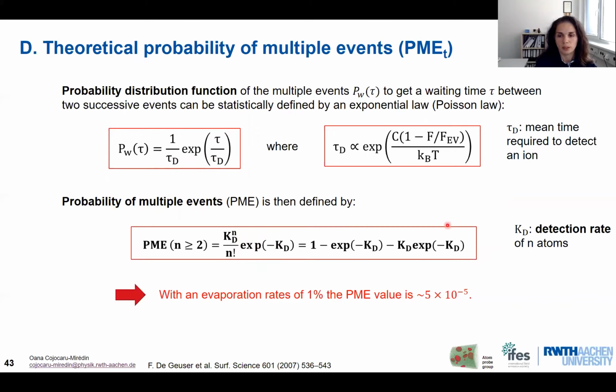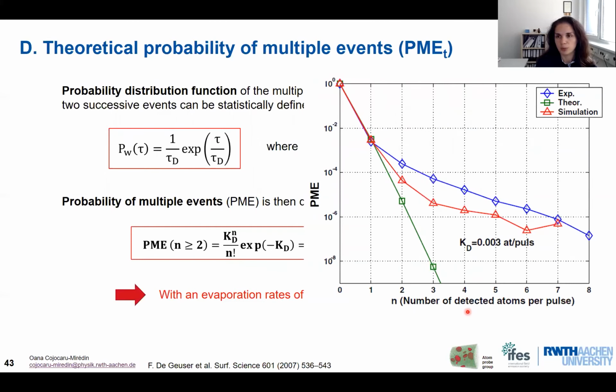If we then take, for example, the detection rate of about 1%, which we usually use for atom probe experiments, we see that we end up having a theoretical probability of multiple events which is rather low. This is 10 to the power -5. So this is a very low probability. Let's compare now with the experimental value. The green line represents the theoretical value, and this is very low. If we compare with the experimental value, we see that we have a really very strong shift.